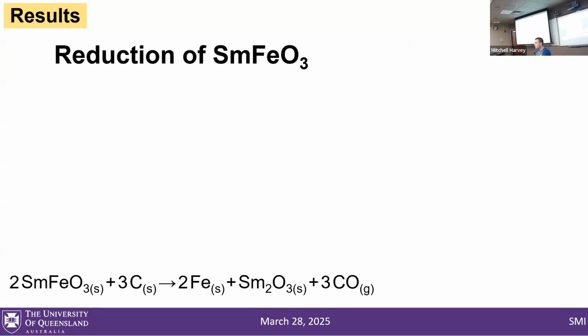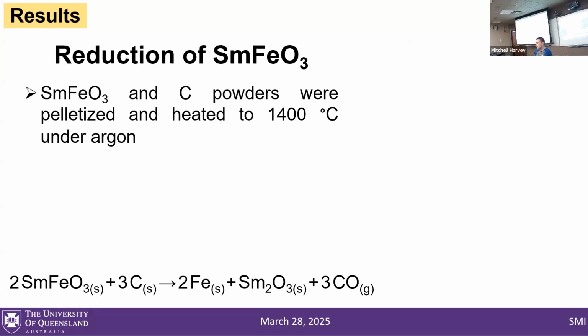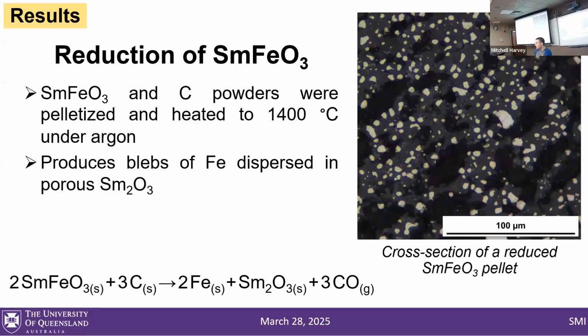Our samarium ferrite plus carbon goes to iron metal plus samarium oxide plus carbon monoxide. And to do this in the lab, we just mix the samarium ferrite and carbon powders, pelletize them, heat them up to 1400 C under argon, and then this is what we get.